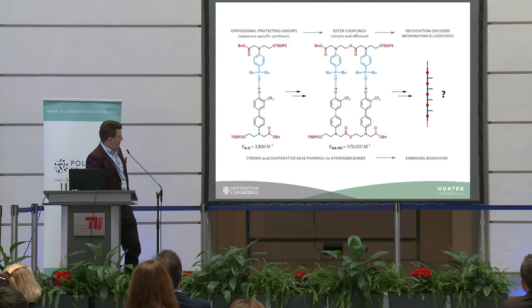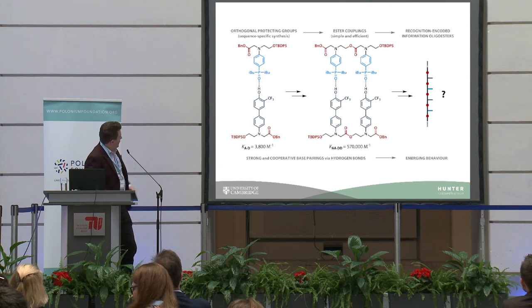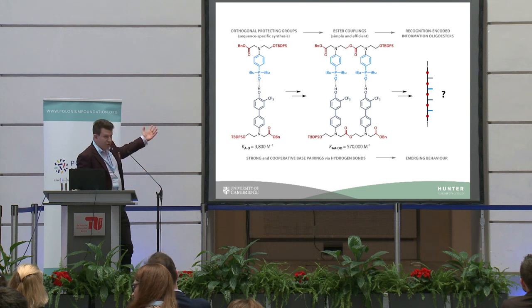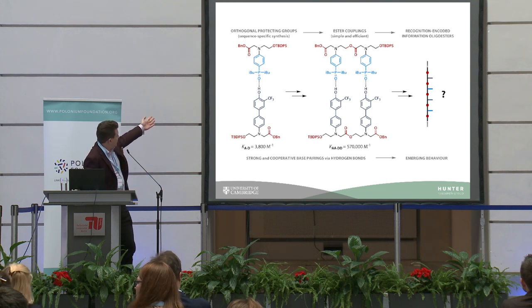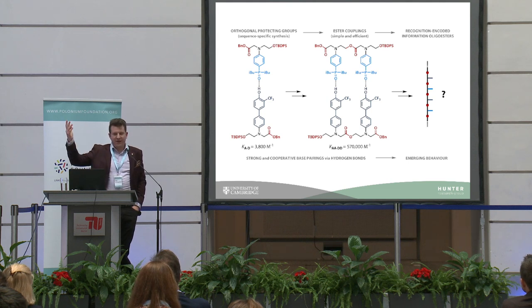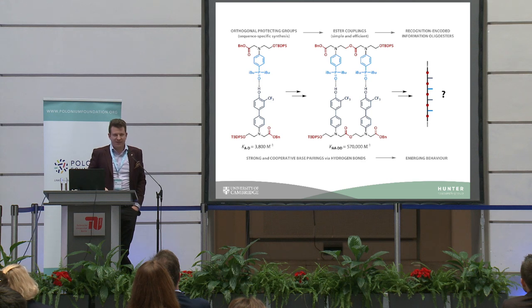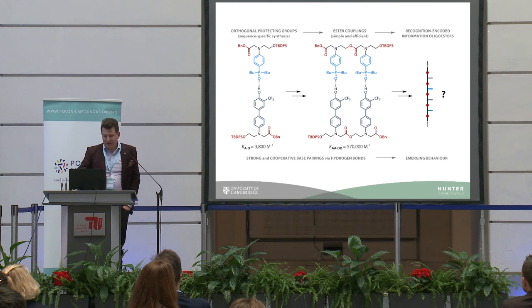To summarize: we synthesized building blocks for information molecules — molecules that can read, write, and copy information — that are easily synthesized and scalable. We observe that they form closed duplexes without folding, and their longer-chain behavior resembles what RNA would do. Starting from two monomers — an alcohol and a protected acid — we can easily form esters of increasing length that contain information, and emergent behavior appears. They could be used for evolving materials, catalysis, or other applications. Notably, they are soluble in organic solvents, which is complementary to DNA which is soluble in water.